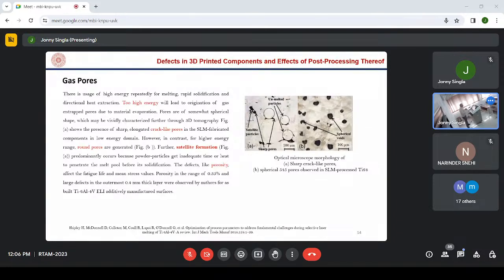Second is the gas pore. There is usage of high energy repeatedly for melting, rapid solidification and directional heat extraction. Too high energy will lead to origination of gas and trapped pores due to material evaporation. So if you use energy density function on the lower side, then lack of fusion. If you use energy density function on the higher side, then there will be evaporation of material and it will lead to gas pores. That means higher energy density is also not desirable, and lower heat input is also not desirable. So you have to keep it in the optimal range.